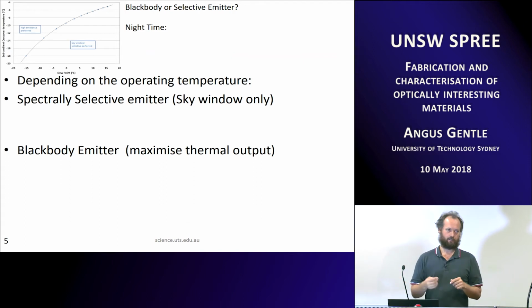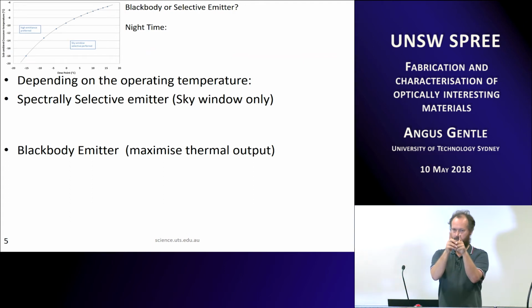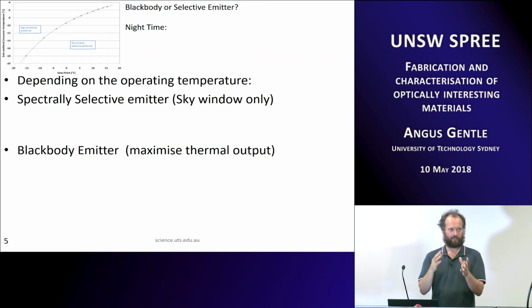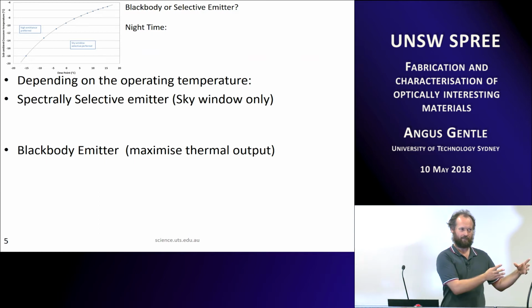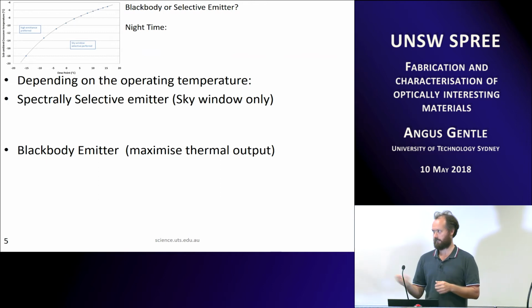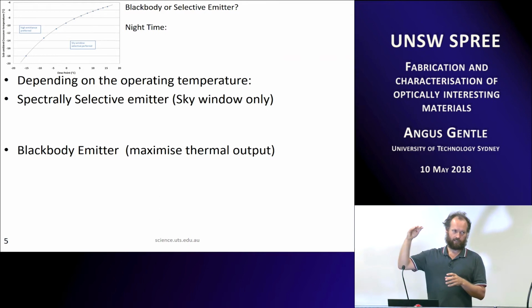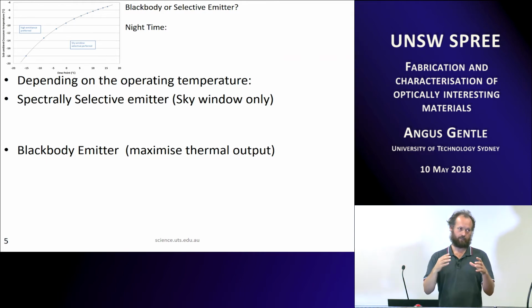So if you've got two surfaces that go out at the same time, the selective emitter will cool slower at first than the black body, and then the selective will take over once you get colder down. So it's sort of this trade-off, but most of the time you're not going to get into that regime unless you've got something where you're trying to just get very, very cold temperatures with very low thermal mass. So yeah, if you're doing solar panels, really, really high thermal emittance is what you want to aim for. And if you end up with a trade-off where you can't get really high at all wavelengths, you just want to make sure that in the sky window it's really high at least. So with glass, for example, there's a peak in the reflectance right in the middle of the sky window, so you really want to get rid of that to make it work better to emit.